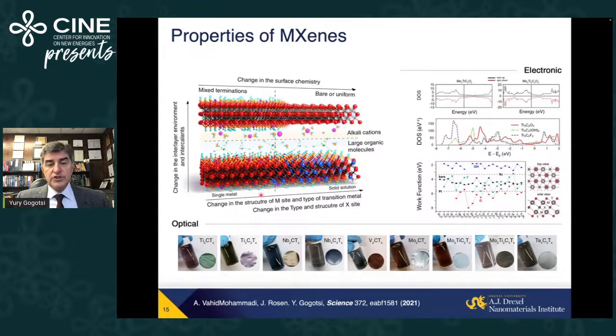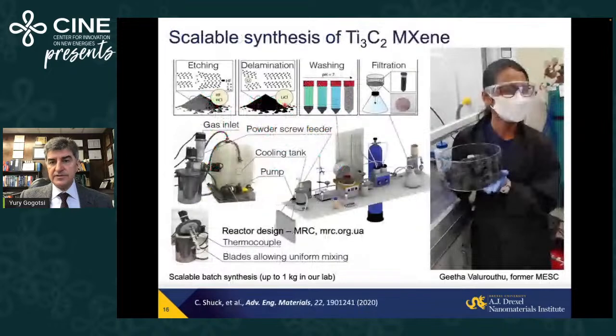Now, let's look at change in surface termination. You replace hydroxyl groups, say by annealing in vacuum at a couple of 100 degrees C, by oxygen on the surface. And the work function goes from 2 electron volts to about 6 electron volts. So if you're looking for a material with a tunable work function for an electron transport layer for a solar cell or LED or organic LED, you can find the material with the right value of the work function. You can tune it finely by controlling this surface termination on the material.